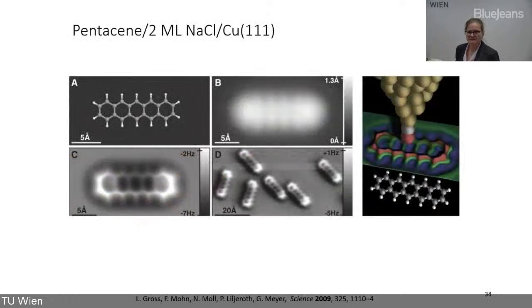This is a very famous result by Leo Gross and colleagues from IBM Rüschlikon, where they put this pentacene molecule on a surface, shown in panel A. In panel B, you see the best STM image you can ever get. It looks fuzzy because what you see in STM is essentially the orbitals. In panel C, you can see the frequency shift that really shows you the molecule like chemists are drawing it. That's a fabulous way of taking images on surfaces with, I would say, the ultimate resolution.